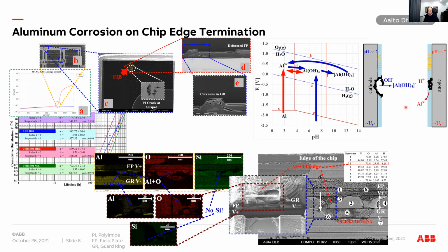So we think that both of these reactions will occur and cause this kind of a pileup of the structure, and finally leading to a breakthrough. And that's actually what explains this deterioration of the leakage characteristics.